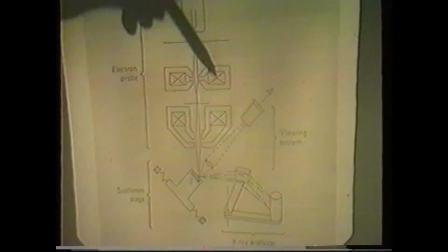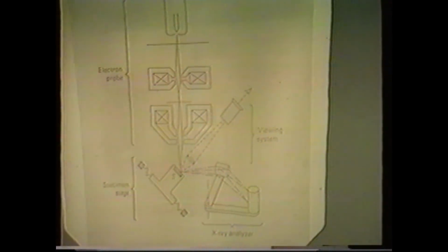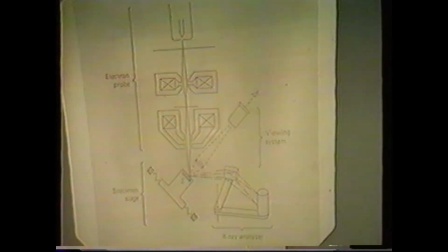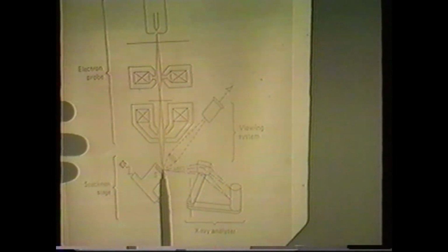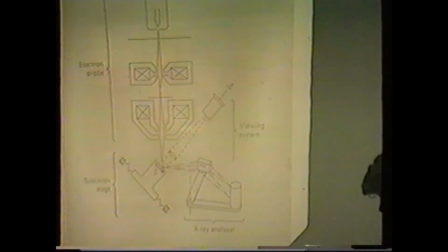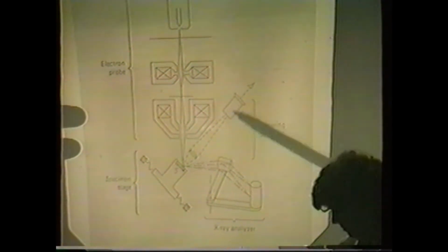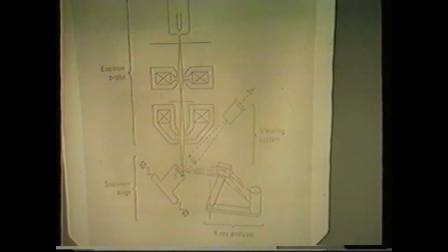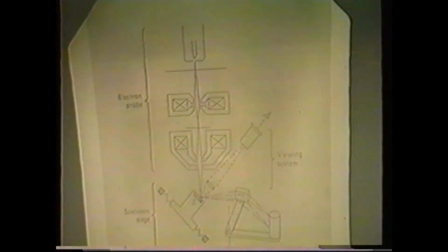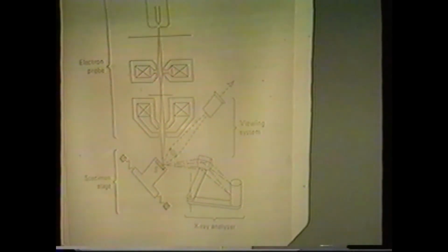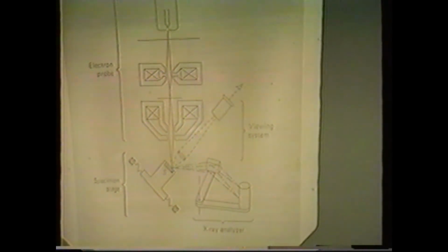They're then focused with the help of some electromagnet shown here, focusing this beam so that the impinging electron beam is only about a micrometer in diameter. With the help of an optical microscope shown over here, we can distinctly focus this electron beam on the various layers of pigment that we showed you on the cross section.